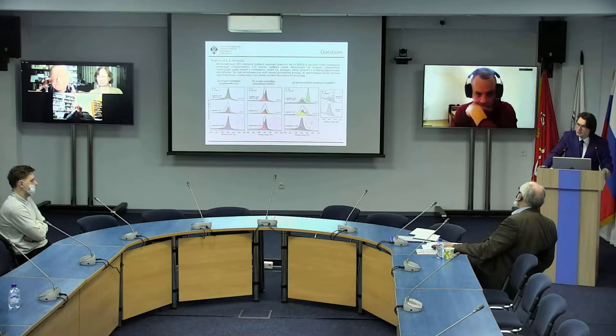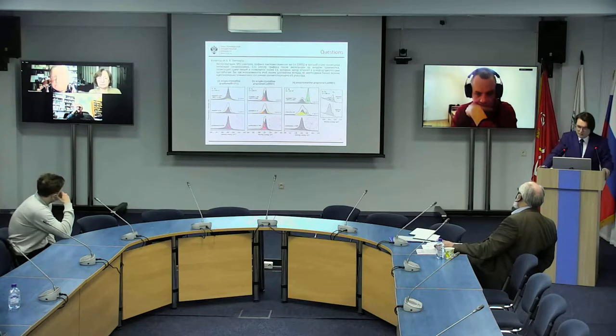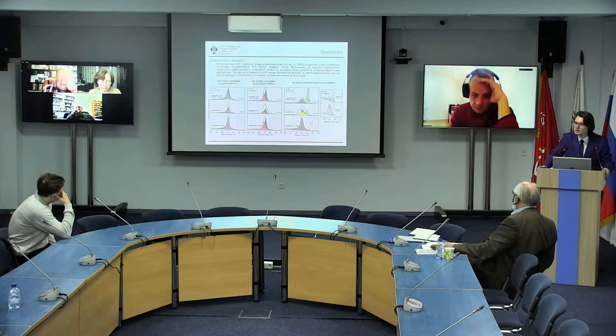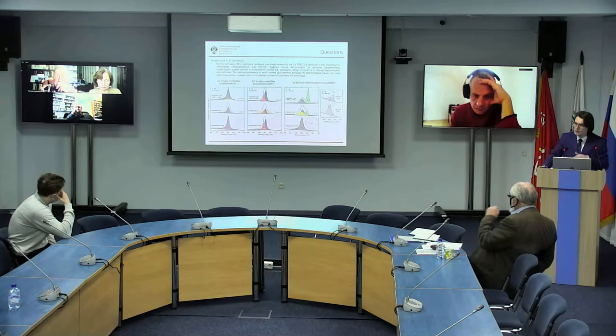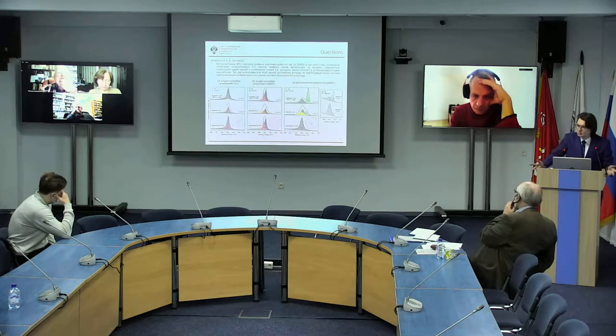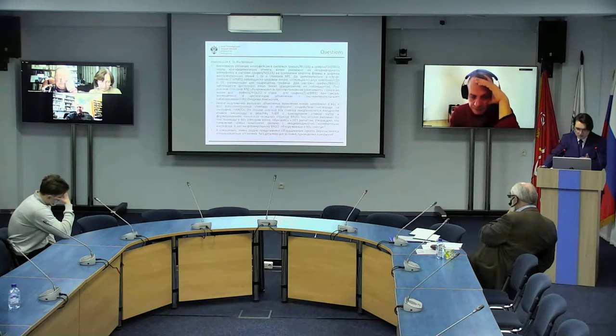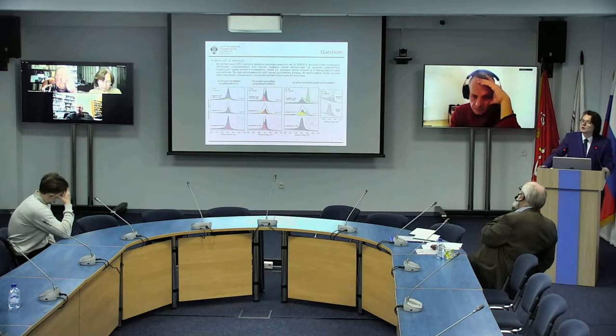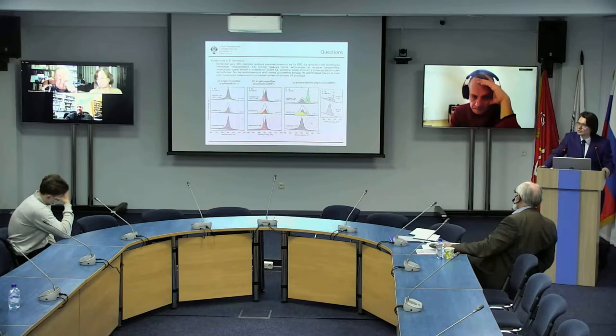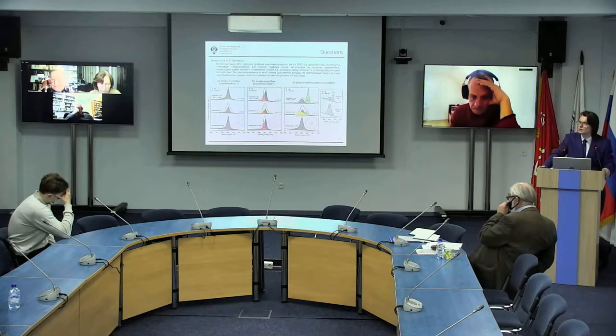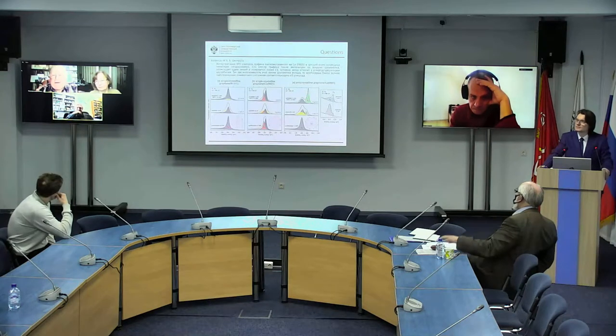This C0 peak is associated with graphene strongly bound with the substrate. When there is an intercalation of oxygen under graphene, under the impact of atmosphere, graphene partially is intercalated with oxygen, and oxygen penetrates under the layer of graphene and disrupts this strong bond between graphene and cobalt. And as a result, we see this shift to the smaller binding energy. And the same was observed in ARPES data when the direct cone restores near the Fermi level. So that's a clear indication that graphene during intercalation shifts to a quasi-free state and there is a certain doping of graphene during this intercalation. So I believe it's quite okay with this shift.